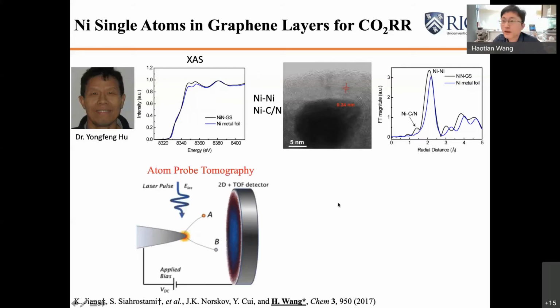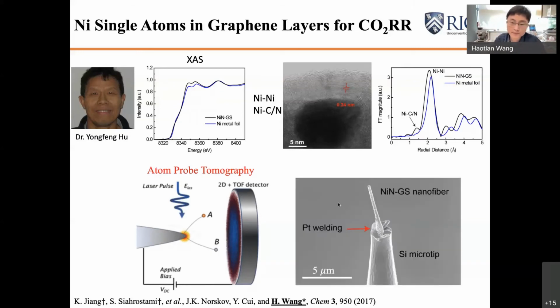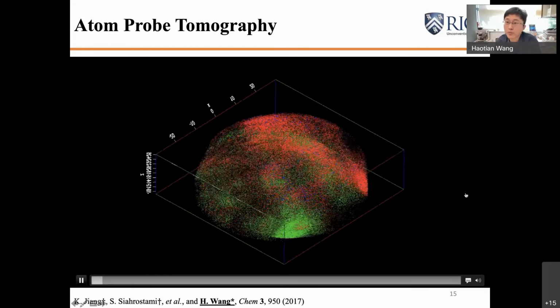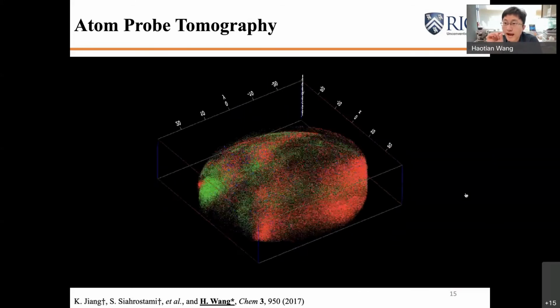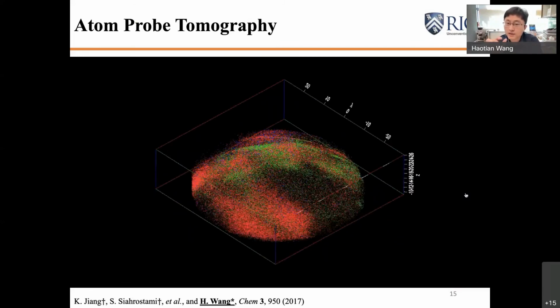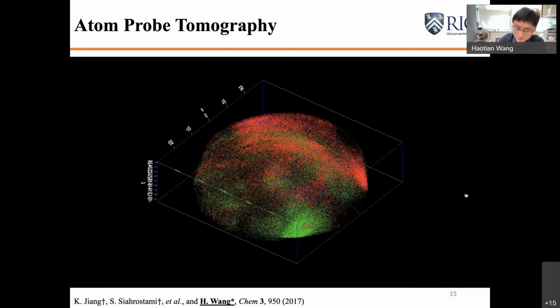Then we utilized a different technology called atom probe tomography, using a very high voltage electric field between the sample tip and the two-dimensional mass spec. And by shining lasers frequently, we can evaporate the atoms, each of the atoms, out of the sample tip, so that we can collect the signal from the two-dimensional mass spec and then reconstruct it back into a three-dimensional tomography. So if you look at this sample tip, as you can see, this is a tomography. Each of the pixels represents one atom, and the red is carbon, green is nickel, and blue are nitrogen atoms.